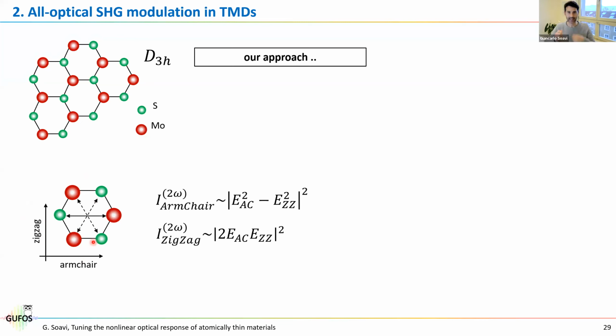And now you can do all the algebra, so you can take the second order matrix and do all the calculations, and you will see that if you want to generate second harmonic along the armchair direction, then you need an incoming electric field either along the armchair or along the zigzag. So the second harmonic along armchair is given by the difference of the square of the incoming electric field. But if you want to generate second harmonic along the zigzag direction, then you need the product between armchair and zigzag. So it means if you arrive at 45 degrees, then you will emit exactly at zigzag direction.